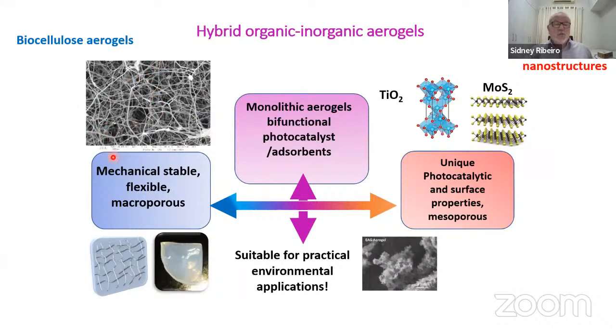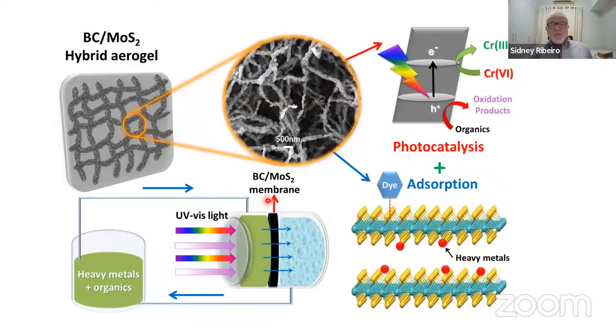The cellulose aerogels world with mechanical stability, flexibility, and macroporosity, and the inorganic phase, with the wonderful, unique properties of these inorganic phases in photocatalysis and also in surface properties. So these new materials are suitable for practical environmental applications. So we did that. We used this membrane in order to decontaminate water, and the membrane was able to absorb organics, dyes, and also to remove heavy metals, for example, chromium-6. When you shine, you will degrade the organics by photocatalysis, and you will reduce the chromium-6 to chromium-3 in order to remove it from water.